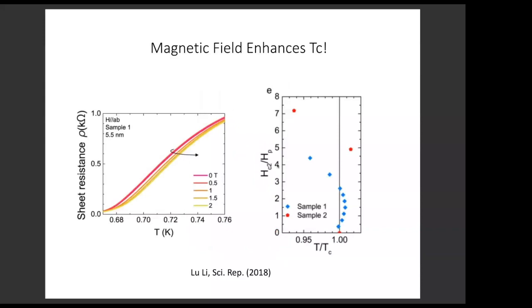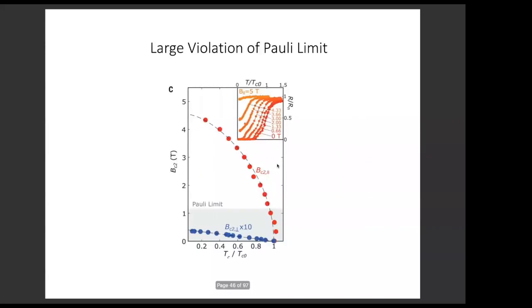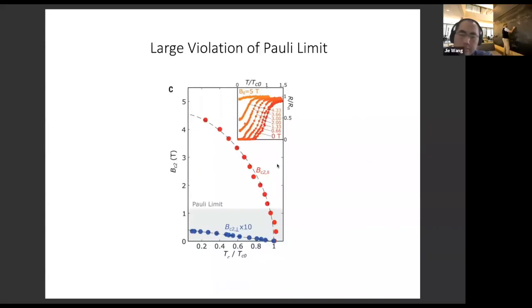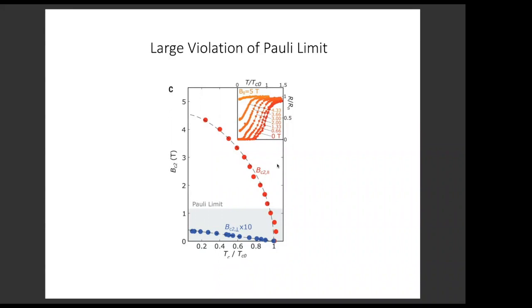Now, this is what caught my attention. If you look at the previous slide, this is data from Pablo's group. You see that at a small magnetic field, the TC actually seems to increase under a magnetic field before it decreases again, right? There are essentially only 3 data points, so maybe one should not make too big a deal out of it. And certainly the authors didn't even comment on it. But then next slide.